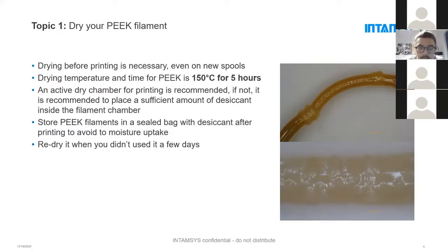how dry it was when the manufacturer sealed the bag, and also a sealed bag is no guarantee against moisture, as even the bags still let some moisture inside. We do recommend 5 hours at 150 degrees Celsius. We also recommend an active dry chamber to keep the material dry within the print. So like slightly heated 70 degrees or better 100 degrees, depending a little bit on how long you want to print, and also on the conditions that you have in the environment.